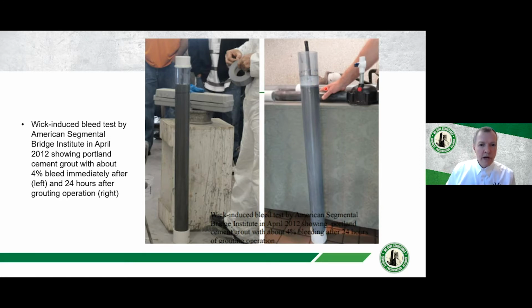And with cement water grout, typically you're going to have somewhere between 3 and 5% bleed, depending on the amount of excess water, and that is going to mean that you're going to end up with 3 to 5% voids when the grout is fully cured. And that's assuming that everything is properly done by the contractor and there are no voids because of air pockets, or the tendon was fully full before setting started up. So this is one issue that can lead to problems: voids.